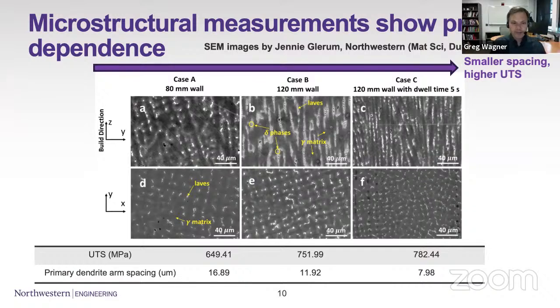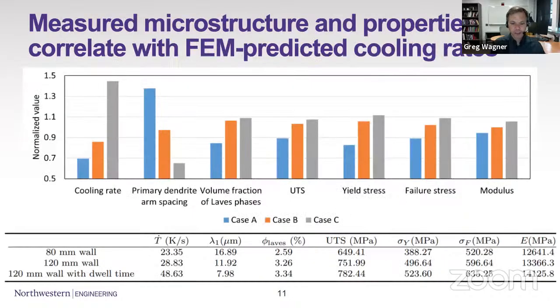Looking a little bit more in depth at that, we can compare that with the simulation data. And again, this particular result is not so surprising. If we look at data across those 3 cases, and compare first the computed cooling rate, so this is from our finite element simulation, these bars on the left. Everything here is normalized according to the mean, so 1.0 would be our average case across these. Across these 3 cases, the cooling rate is increasing. It's really just a result of the fact that there's a longer amount of time in between each laser pass or between each build pass at this scale. So the cooling rate is increasing across those 3 cases.